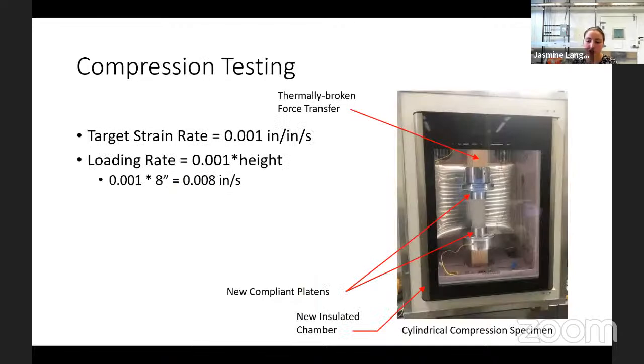So this is what the compression testing setup looked like. One of our platens was fixed and one of them was compressing. We had our platens at the top and the bottom of the ice sample, and then our ice sample on the inside. Our target strain rate was 0.001 inches per second. To determine our loading rate, we multiplied our target strain rate times the height. So if we had a cylinder that was 8 inches tall, our loading rate was 0.008 inches per second.